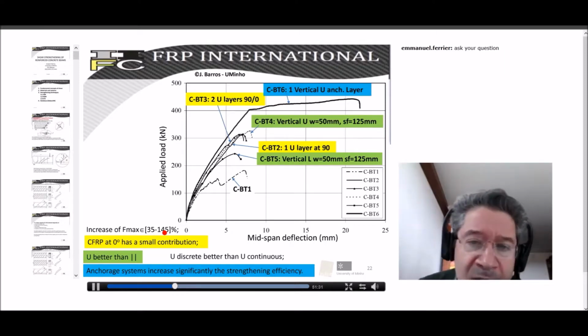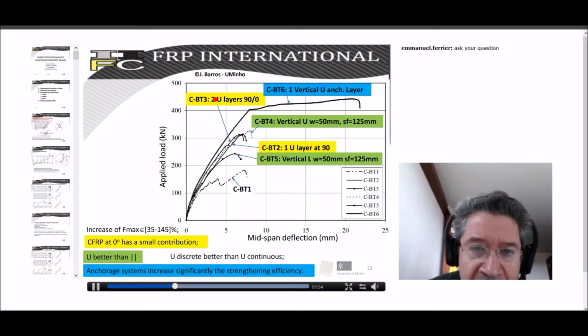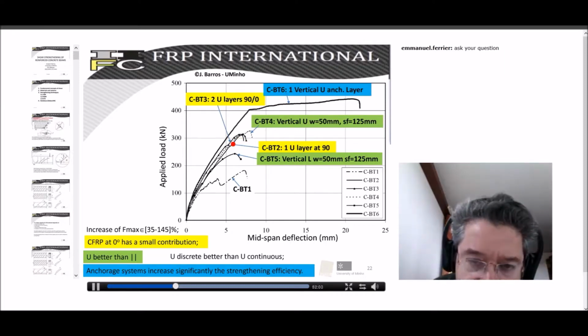A very important aspect is the comparison between the beam with 2 layers in U configuration, where one of the layers has the fibers in the horizontal direction, 0 degrees, and the response of the same beam where we only applied 1 layer in vertical, without a horizontal layer. We realize that the values are almost the same. So the layer in the horizontal direction has a very small contribution to the shear capacity of the beam.